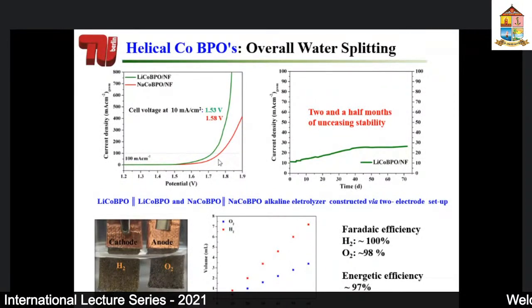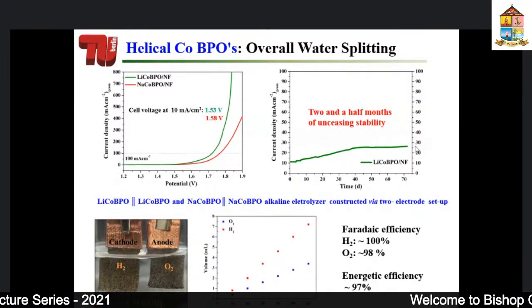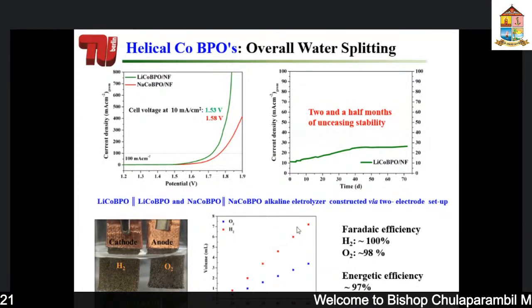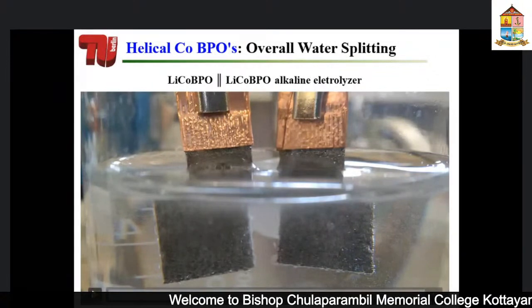Okay, so since we understood what's going on, we took this as an example, and we constructed an electrolyzer. As you could see, this determines how efficient your water electrolyzer is. We could run it for 2.5 months without any problem. We had a very stable and high current, so this is very nice. This is the picture of how it was assembled, and this is the amount of hydrogen and oxygen produced. Note that hydrogen is always double the oxygen, just because you are producing double the amount of hydrogen in water.